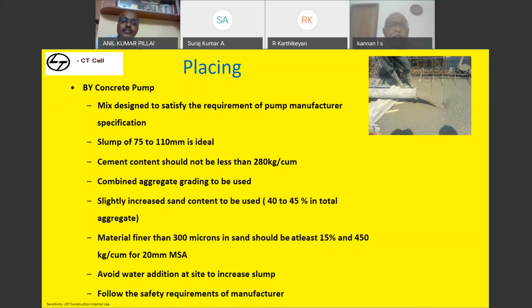Combined aggregate grading needs to be used. Slightly increased sand content, maybe 40 to 45% of total aggregate, if it is there. Depending upon the fineness modulus, you need to decide and add. In normal practice, when you are making an all-in aggregate grading, suppose if you are using a 20 mm aggregate with an all-in aggregate grading, 20 mm should pass 95 to 100. They say 4.75 is 30 to 50. That 30 to 50, if you are able to make something around 38 to 42%, your mix will be a perfect mix, because the 4.75 is a transition zone between your coarse and fine.